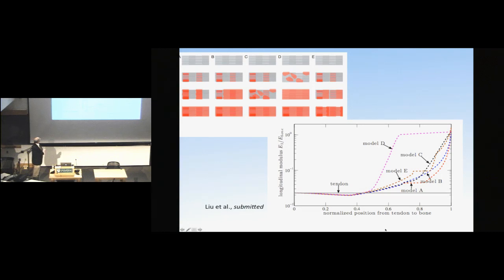Now the 4 models that I believe the most, where mineral accrues on the inside of a fibril prior to accruing on the outside, all have something of a delayed percolation, which allows for the transverse stiffness to rise faster than the axial stiffness. And then this model D, which has mineral accruing on the outside first, has a much sharper percolation threshold and much sharper rise in stiffness.